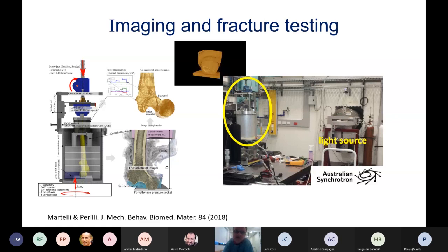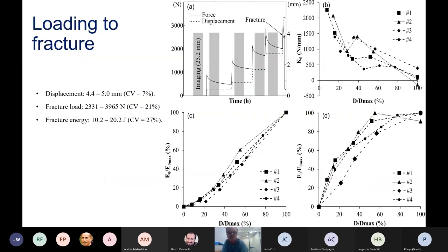What we are seeing here is the experiment. We have a compressive stage that you see on your left, and a micro-CT system at the Australian synchrotron, where we could image the entire bone under a progressive load up to fracture, and the animation shows you a volume of the bone from the images.